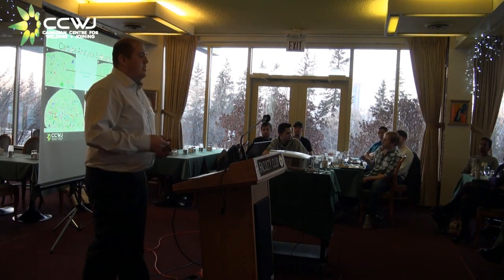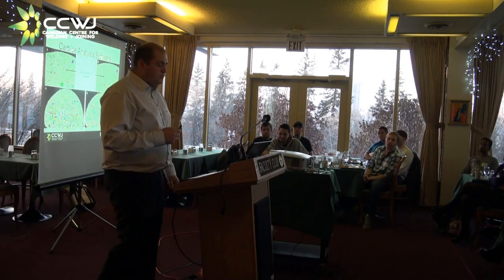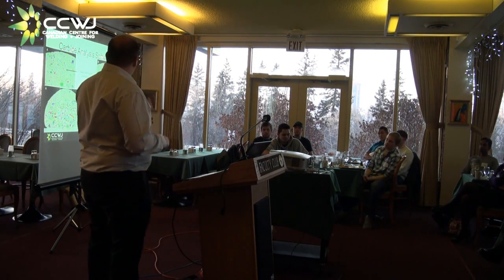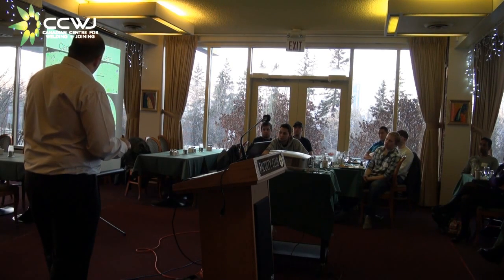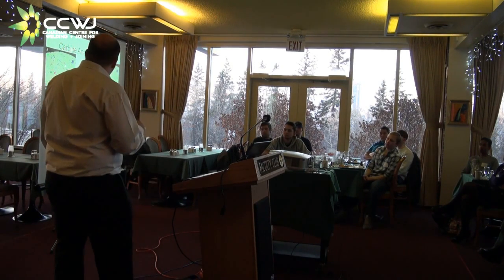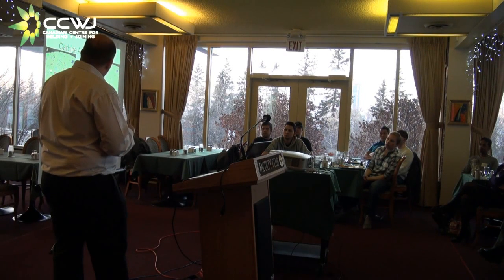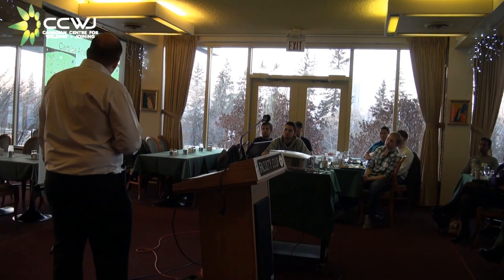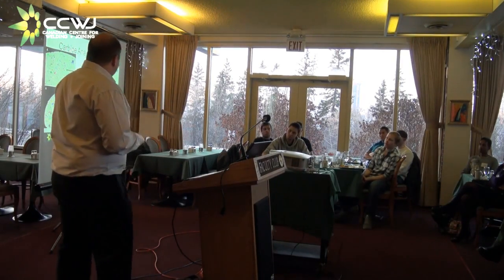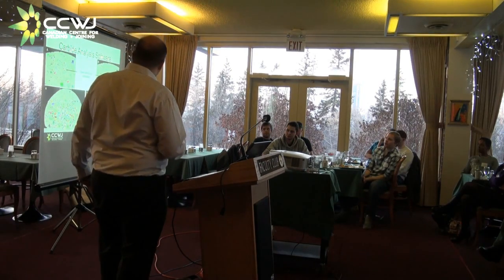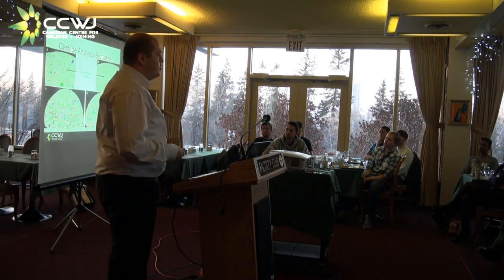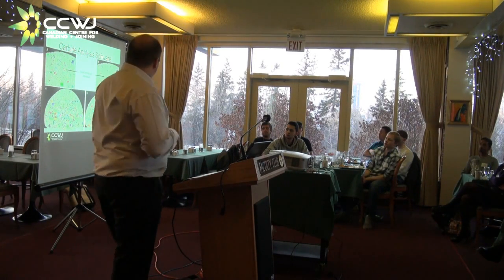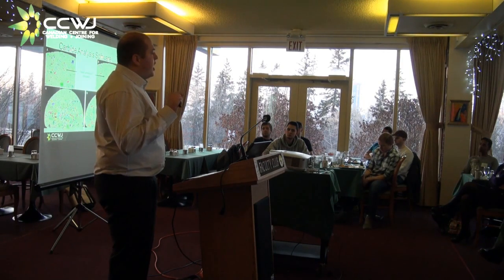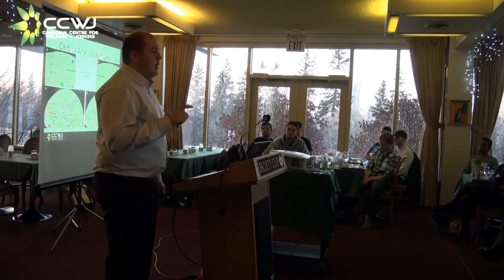And as it turns out, there's a drastic difference in the wear and the carbide volume fraction as we do this separation. So you can see here in A, all these funky colors don't mean anything. They're just random colors. They don't have anything to do with the size range. But as you can see, we've measured every little carbide. We've got our big primary ones that survive during welding, and then we've got all these little tiny angular ones, which are a result of overheating. They're reprecipitating. Now, if we do some operations on the image, you can see we still have highlighted our primary ones, which are going to give us our good wear performance, and separated them from our detrimental little tiny reprecipitated ones, which do not improve our wear performance.